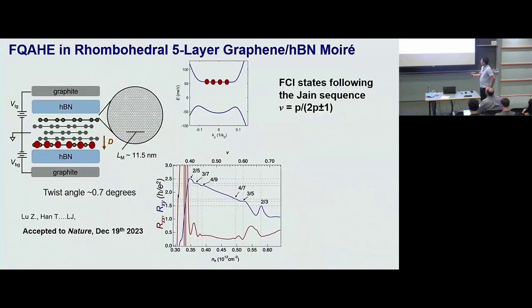Okay, so a brief reminder of what we have seen in the pentalayer rhombohedral graphene hBN Moiré system. When we push the electrons to the layer that's away from the Moiré, we observe integer and fractional quantum anomalous Hall effects. At that time we had 6 fractions, and you may have noticed that 5 of them look sort of similar, in that Rxy changes monotonically. Of course, 2/5 is slightly different because it's on the boundary, but most of these fractions go down monotonically and slow down at a plateau before going down further.